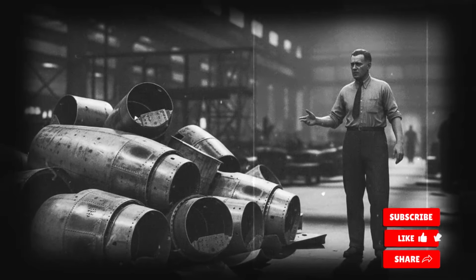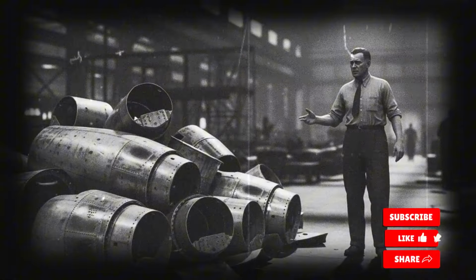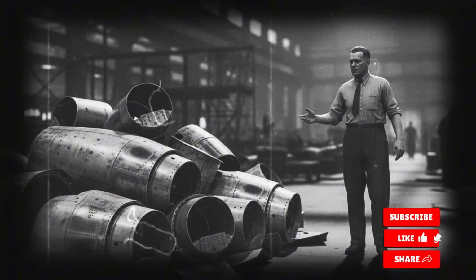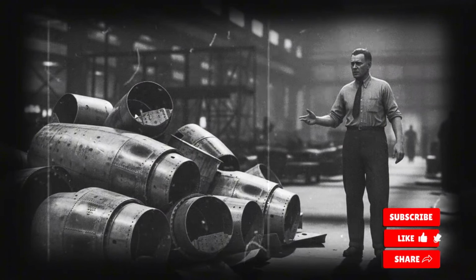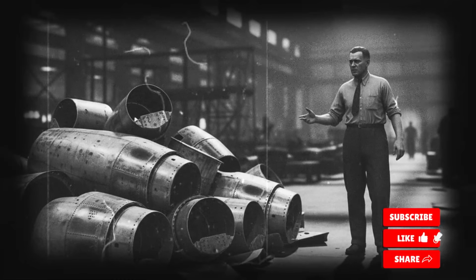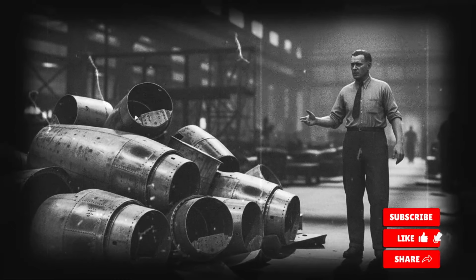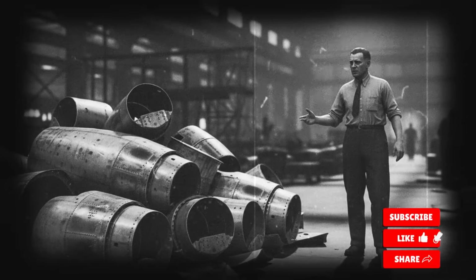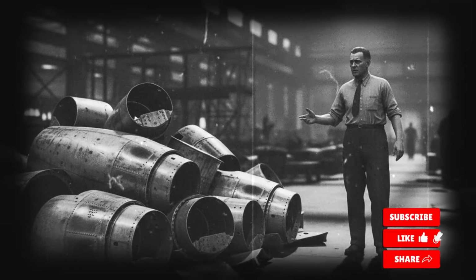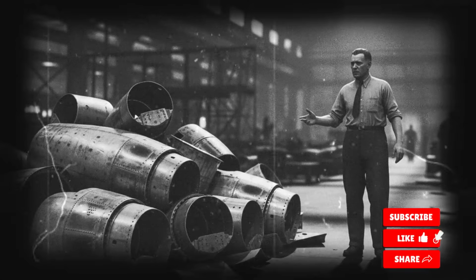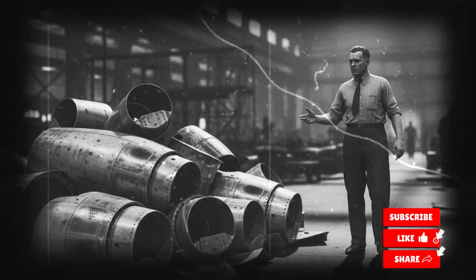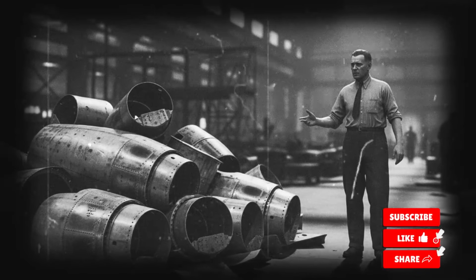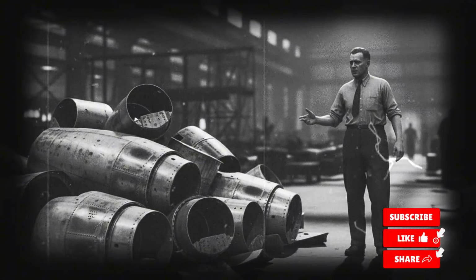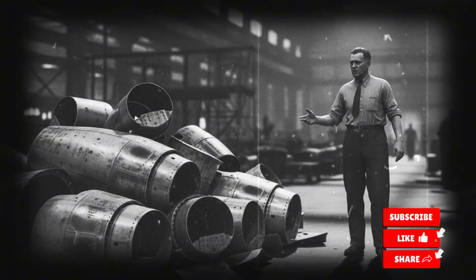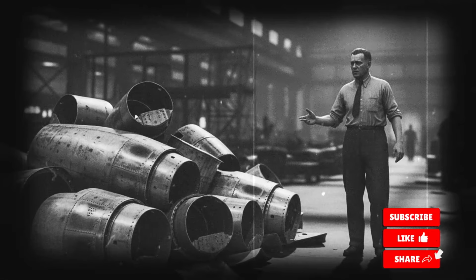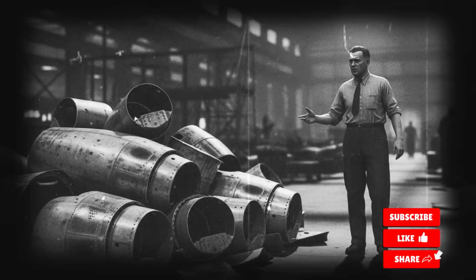"It's brilliant, actually. Inefficient in terms of gas consumption, but it solves the oxidation problem that usually ruins fast aluminum welds." Major Zeller performed stress calculations based on the measured heat-affected zone properties. His conclusion contradicted the catastrophic failure predictions. "These joints retain approximately 85% of parent metal strength. That's better than many riveted joints. Combined with the elimination of stress concentrations from rivet holes, the overall joint efficiency might actually exceed riveted construction."